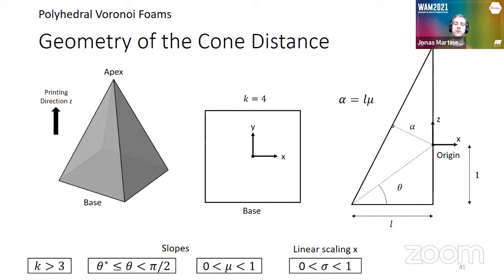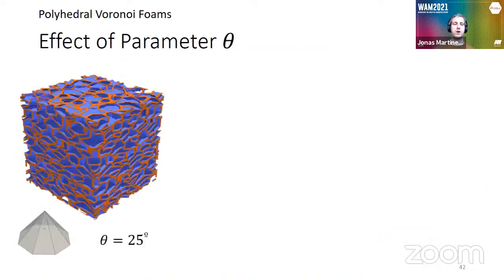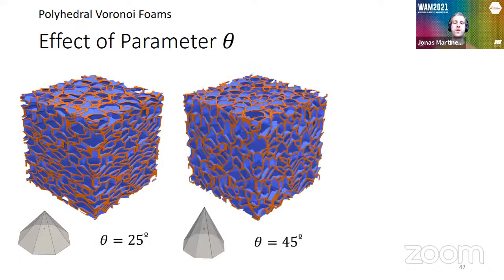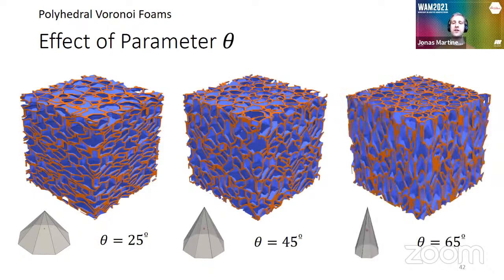So I'm going to put all these parameters in a visual action. And of course, a rotation. This is important. We can also rotate this cone. So let's have a look. Here you have a cone below with the parameter theta 25 degrees, and you have the resulting stochastic microstructure. So as you can see here, you have something that is flattened, but your Voronoi diagram is always self-supported up to this overhang angle. As you increase theta, for instance, to 45 degrees, you will see that this flattening elongates and you get things more elongated into the printing direction.